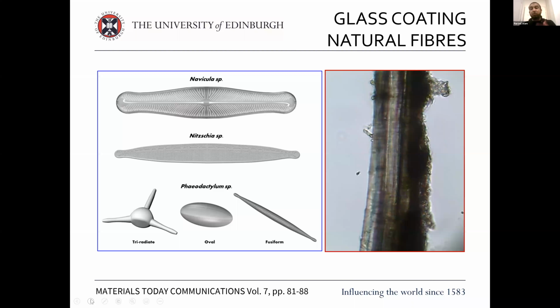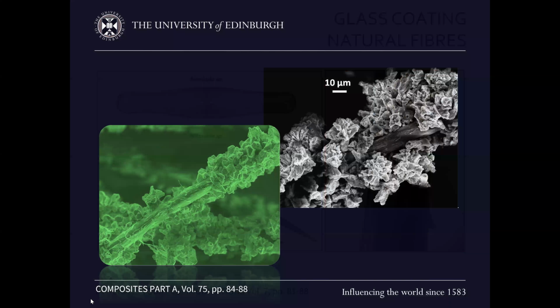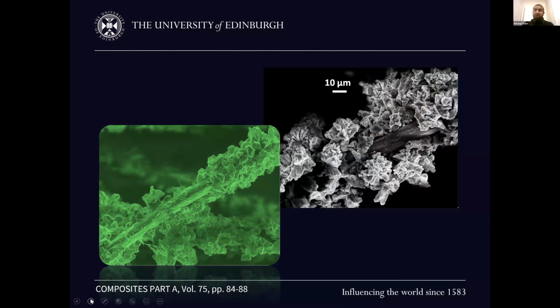And we did this also using coralization methods. So we mimicked the corals. They basically form these hard exoskeletons. So we basically formed, using polymer templates and calcium carbonate reactions, these flowery crystals on natural fiber surfaces. We embedded them into polymers, and we found that we pretty much doubled the strength and stiffness of natural fiber composites by doing this.